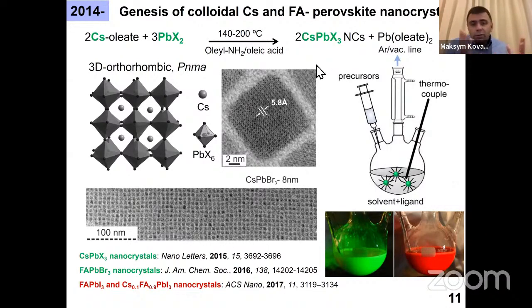So in 2014, we began to work on colloidal synthesis now of perovskite quantum dots. We focused initially on cesium lead halides, fully inorganic. And simply by reacting two very simple precursors, in the presence of such long chain molecules, you produce nanocrystals which are cubic in shape and which are quite monodisperse. And it was easy to extend this simple synthesis to basically the entire family of these lead halide perovskites, which is formamidinium and cesium based.